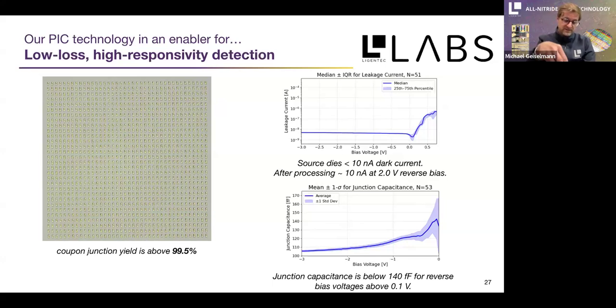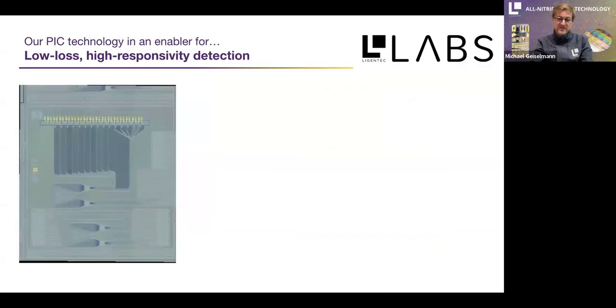So these are the PDs that we pick and place, we call them coupons. And here, all these dots are the PD coupons, and we see that the source dies have similar dark current before and after processing, which assures that this processing step is working for integrating III-V PDs on a low loss nitride circuit.